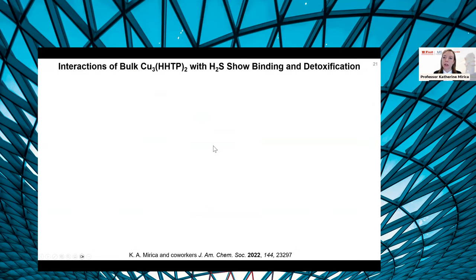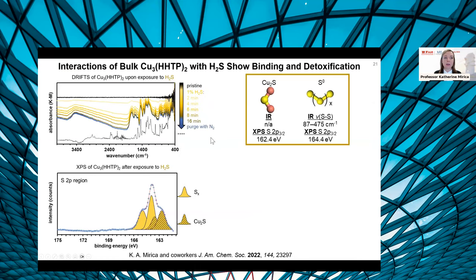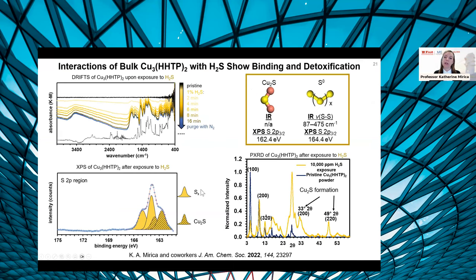Upon interactions with hydrogen sulfide, what we actually see using the same kinds of spectroscopic techniques is the presence of sulfur zero species, as well as metal sulfide, such as copper sulfide in the case of the copper-based framework. The crystallinity of the framework is also retained, but upon these high concentrations of exposure, we do see some diminished intensities of the diffraction peaks corresponding to some framework breakdown, but also indicative peaks of copper sulfide formation, which supports that mechanistic observation.